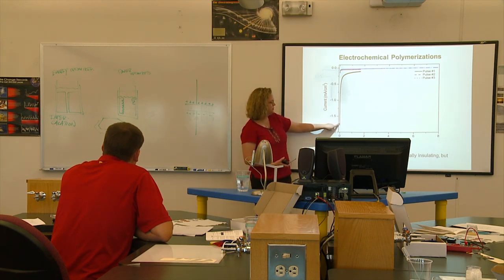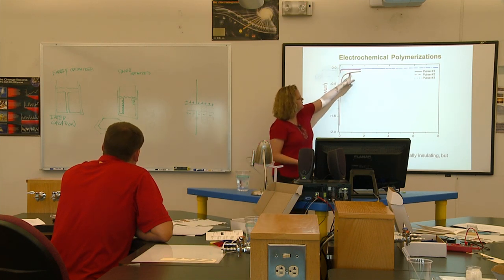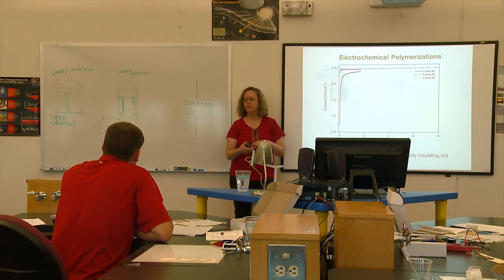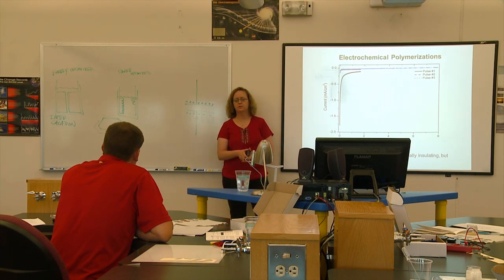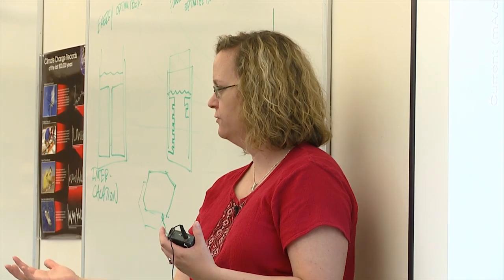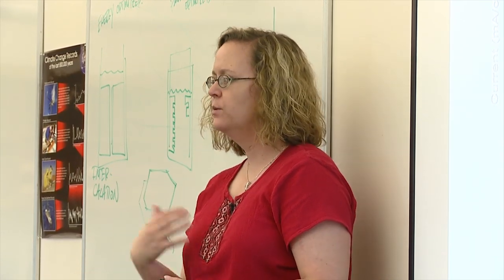So you see that the current starts high because a lot of polymer is being made. Then it drops pretty quickly and it evens out. Then we let it rest because, with these weird shapes, the liquid needs time to replenish itself in these odd shapes. So we turn the voltage off, we let everything rest, then we pulse again.